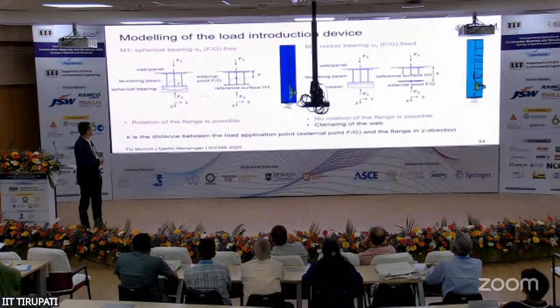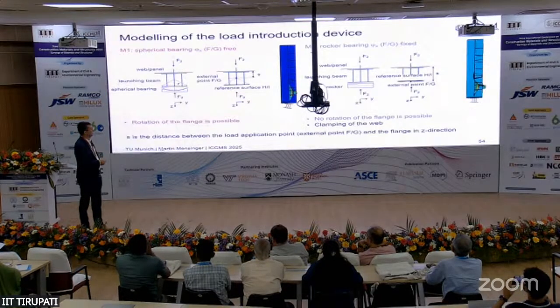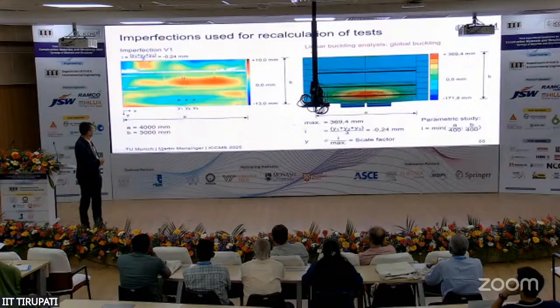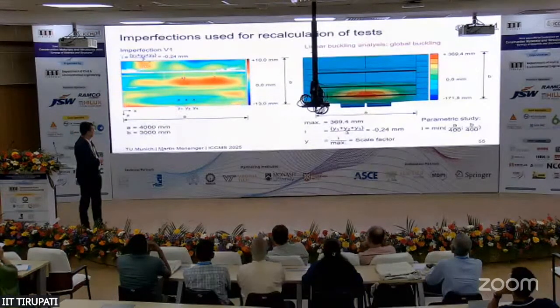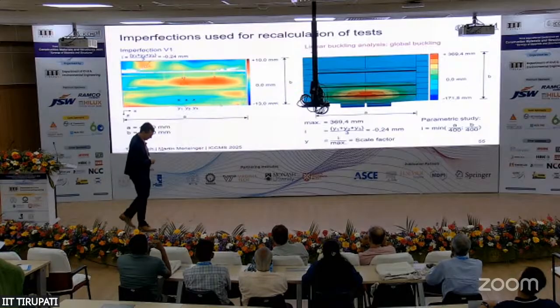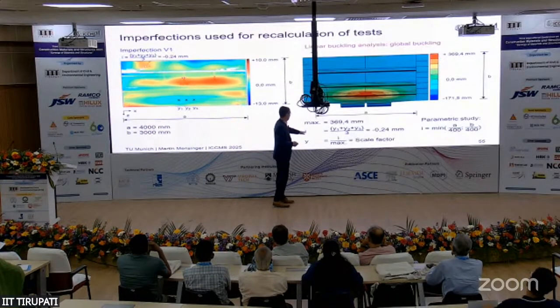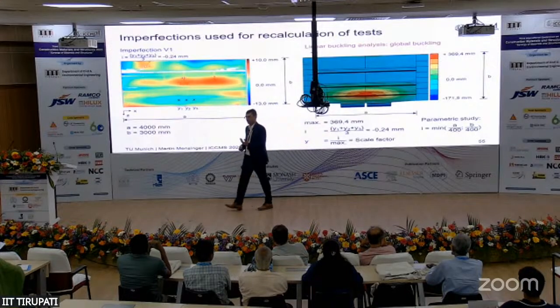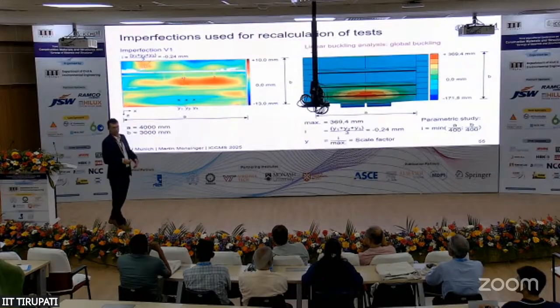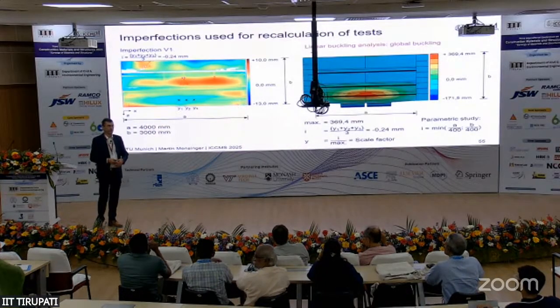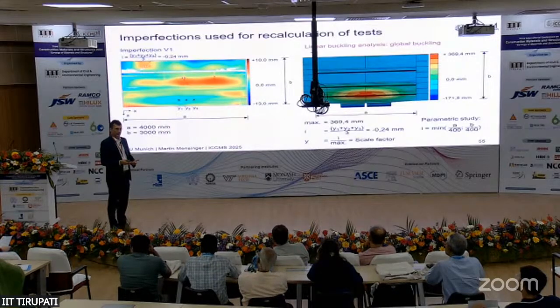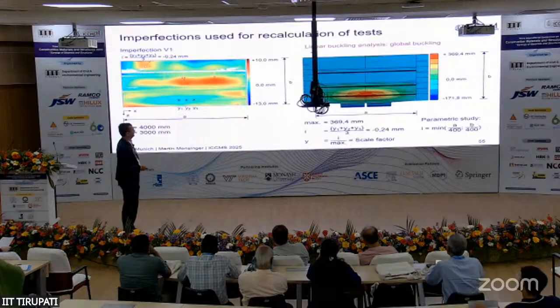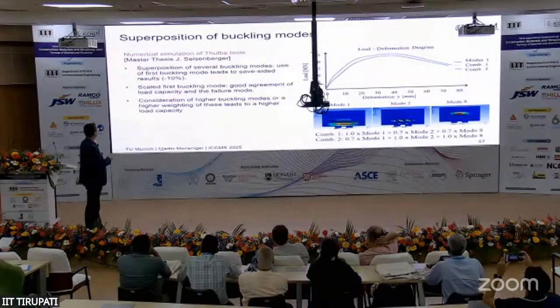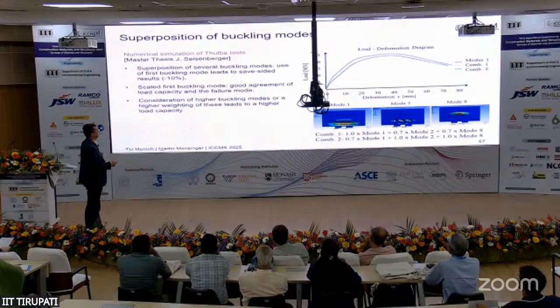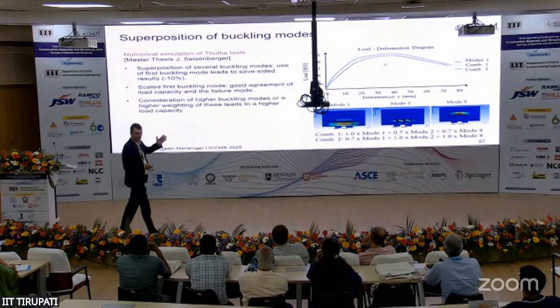What we did, we also considered the 2 different types of bearings in our numerical campaign, and we used different approaches for the numerical calculations. One approach was using the first buckling mode and calibrating it with values from imperfection from the measurement to recalculate our tests. Another was using the overall imperfections and also using combined buckling modes for the calculation of the buckling fields. And this was done with several master theses from Julian Seisenberger, for example, he was looking mainly at the superposition of several buckling modes, and we found out more or less using the first buckling mode is okay.